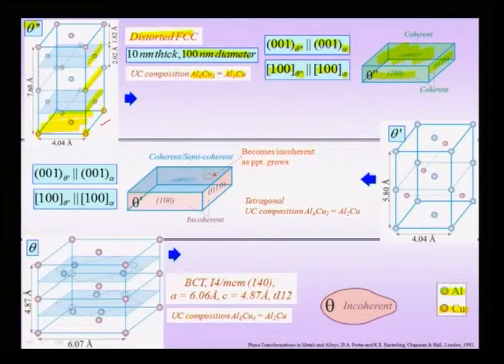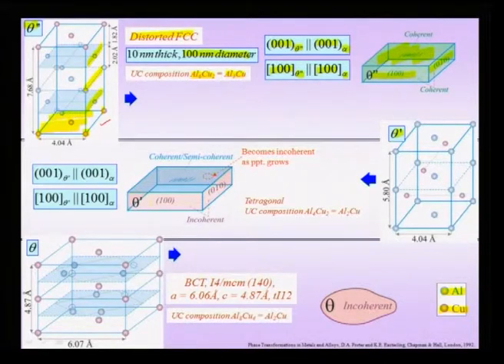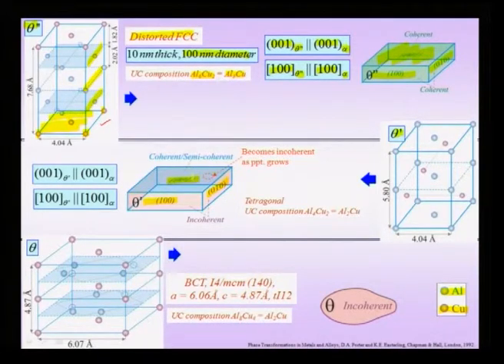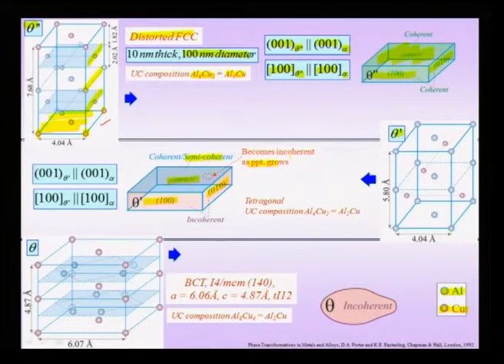This implies that the activation barrier for nucleation will be low, but because of coherency we pay in terms of strain energy, which must be supplied during nucleation. The next phase is theta prime, which has a morphology very similar to theta double prime. However, the (100) and (010) faces are incoherent, and while the (001) face may be coherent initially, as the precipitate grows even this becomes incoherent progressively.